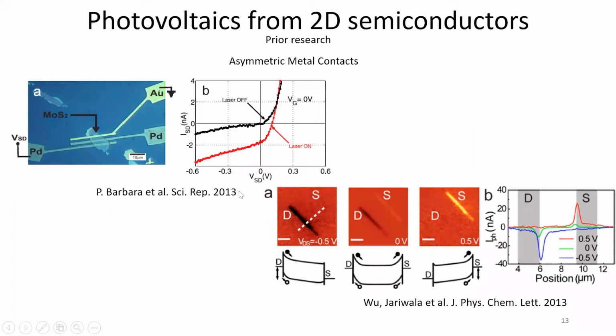We went on right after that in the same year, and this was back when I was doing my PhD. We proved that this effect is mainly localized at the contact because of the Schottky junction, and that it is indeed photovoltaic in nature, because as you apply the bias, you can kill the photovoltage or photocurrent at the contact. So certainly it was true. Now, after that, of course, there was an explosion in the amount of research on optoelectronic devices, broadly speaking, from 2D semiconductors.